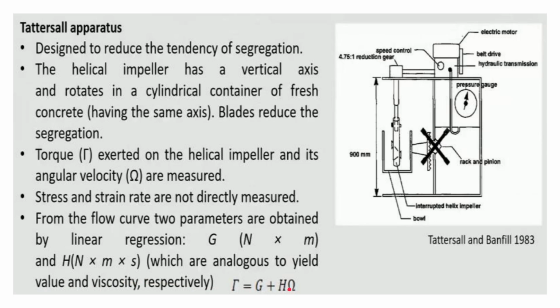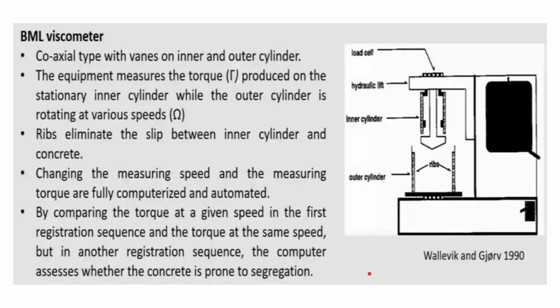So the equation comes to be tau equal to G plus H omega, okay. In the case of the BML viscometer, this is a coaxial type with vanes on the inner and outer cylinder, right? The equipment measures the torque tau produced on the stationary inner cylinder while the outer cylinder is rotating at various speeds omega. Ribs eliminate the slip between the inner cylinder and concrete. Changing the measuring speed and the measuring torque are fully computerized and automated.